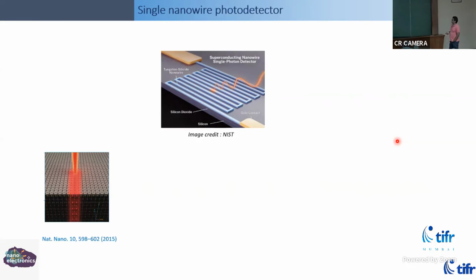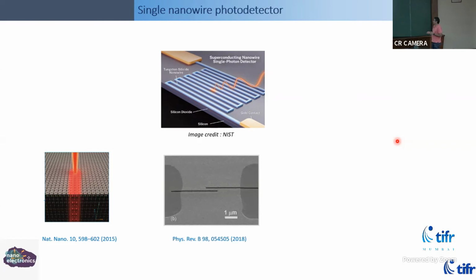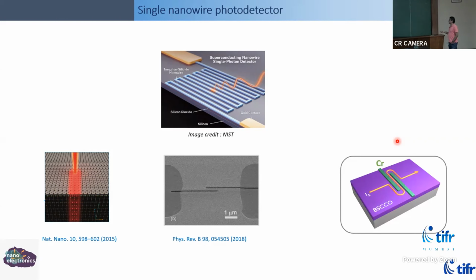So in these kind of photodetectors, people have been working with these high temperature superconductors using a route which is basically cutting. You take a high temperature superconductor, and with some beam of either helium ions or focused ion beam of gallium, you try to cut the material. And that actually is, as I already told you, these materials are extremely sensitive to degradation of the oxygen stoichiometry. But that hasn't stopped people from trying to essentially make small wires of high temperature superconductor by cutting it. What we, in our earlier work that Sanad did, was we figured out that there is an interesting way, once you get it down to